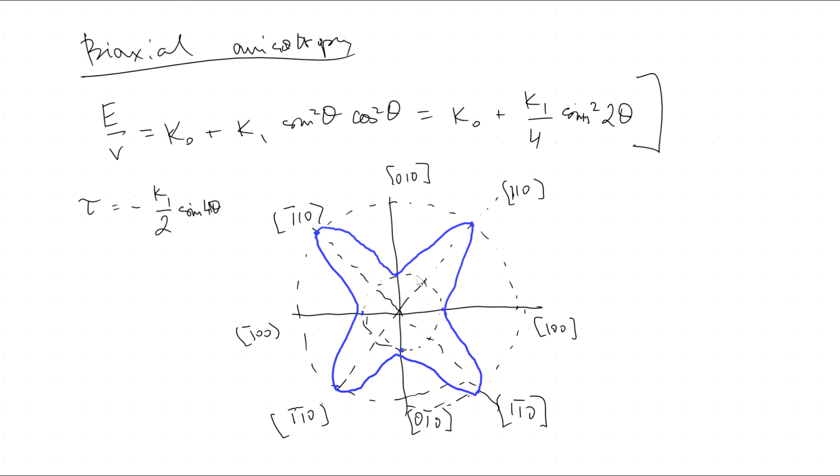So this system has several stable states. It has stable state for magnetization to point this way, that way, this way, and that way. And in this case, it is equally stable. So we can have magnetization pointing to the left up, right up, left down, and all of those would be stable. So you can think of this as our theta, this is 1, 0, 0, 0, 1, 0, magnetization, and this is angle.